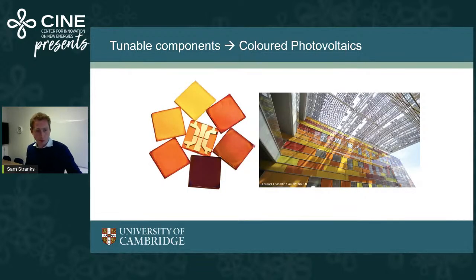Because these materials are quite tunable, we can change the chemistry, change the composition of these materials, and move from something that's, this is a pure iodine metal halide perovskite, and then adding bromine fractions, you can see you can change the color of the absorption of the solar cell or the color of the emission of the material. And this is now a pure bromide. So one can think about building integrated PV where these colored PV panels are designed into facades, for example.